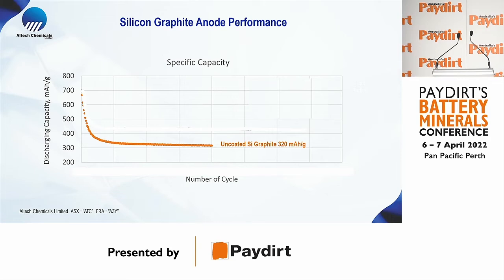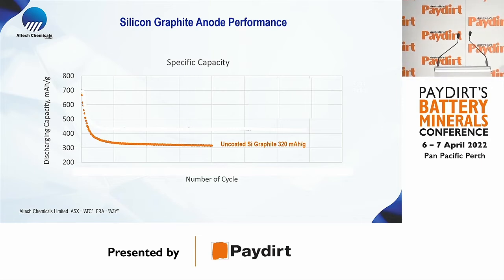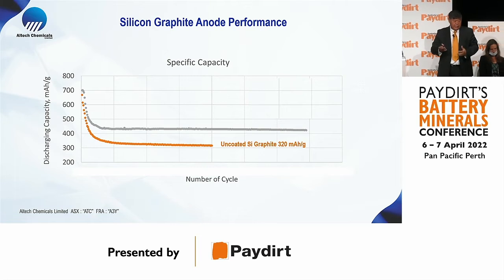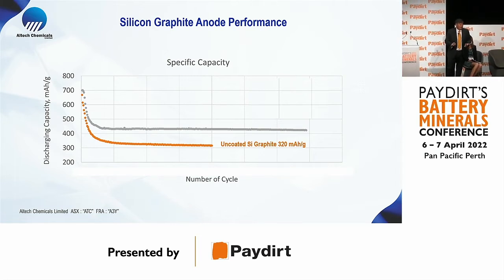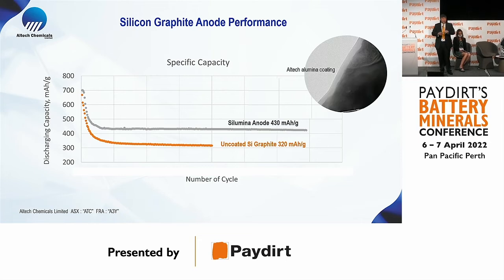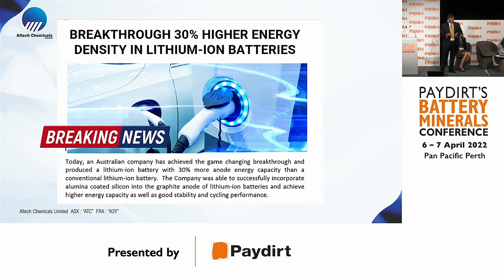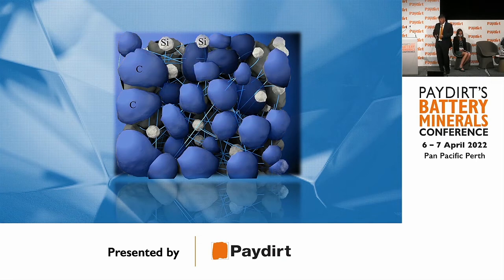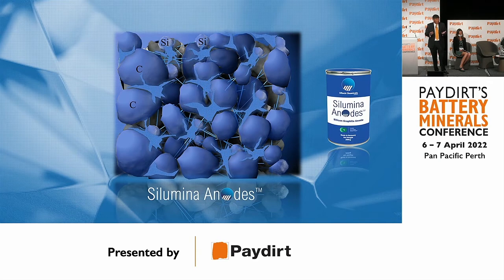So this orange curve is silicon and graphite without any alumina coating. And you can see it starts with a high energy capacity, but drops away very quickly because of the fracturing problem. But by coating the graphite and the silicon, this is what we get. You can see it's now a 30% higher energy density anode. And this is a game changer for the lithium battery industry. We announced the news last year, and our lab is working to push that beyond 30%. So our business is virtually buying graphite material, buying silicon material, coating it with our Alumina technology, and putting it together as a product we call Silumina Anodes.